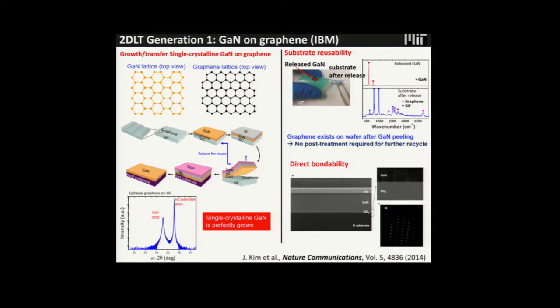Then immediately, because I'm an epi guy by training, I thought, okay, graphene is single crystalline, so why not use graphene as an epitaxial seed? Then you can grow something on graphene and peel it off. So that's what happened in 2013. We used single crystalline graphene, then grew gallium nitride because it's an easy pick. Why did I choose gallium nitride? Because graphene has a hexagonal lattice, and gallium nitride has a hexagonal lattice, just an easy pick. We performed epitaxial growth of gallium nitride on graphene. It was perfect single crystalline. We're so happy about it.